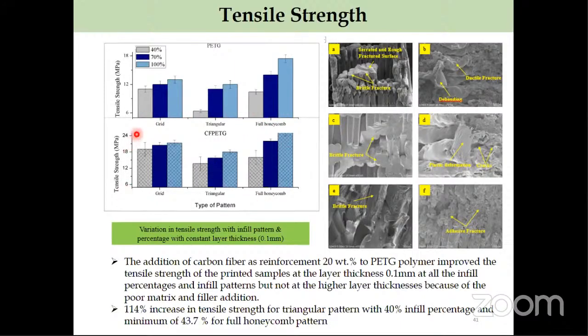And these results are for carbon fiber reinforced PETG, and we could see that the addition of carbon fiber as reinforcement, 20% by weight to the PETG, improved the tensile strength. So that was one result. And another important observation which we found, that at the layer thickness 0.1 and at all infill percentages, this behavior was observed, but not at higher layer thicknesses because of poor matrix and filler addition. And we could see a very good improvement in the tensile strength, which is around 114% for 40% infill percentage. And in the fracture modes, we could see that different fracture modes were observed.